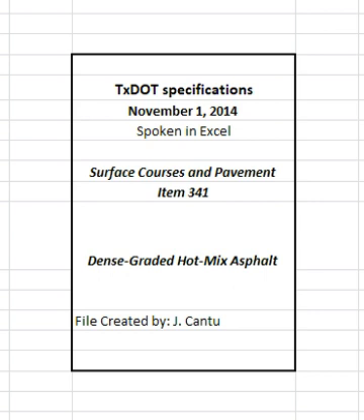Take immediate corrective action if the VMA value for any sublot is less than the minimum VMA requirement for production listed in Table 8. Suspend production and shipment of the mixture if the engineer's VMA results on 2 consecutive sublots are below the minimum VMA requirement for production listed in Table 8. No production or placement payment adjustments greater than 1.000 will be paid for any sublot that does not meet the minimum VMA requirement for production listed in Table 8 based on the engineer's VMA determination.